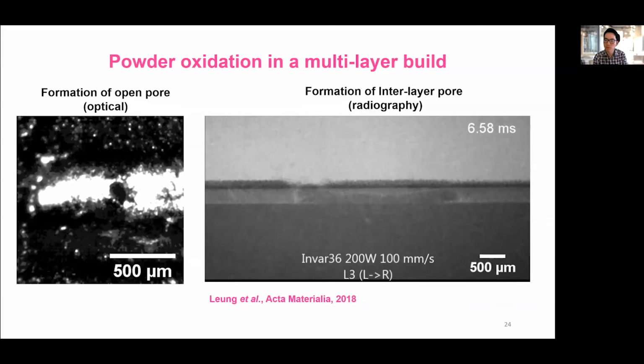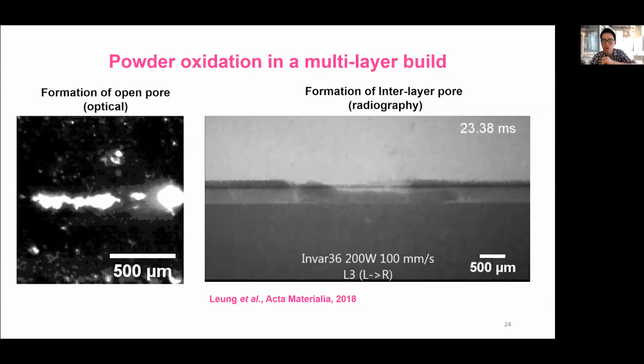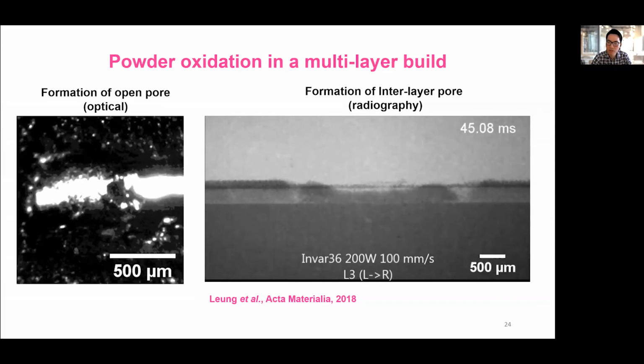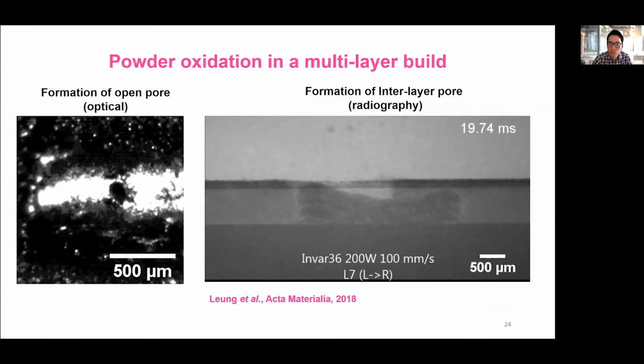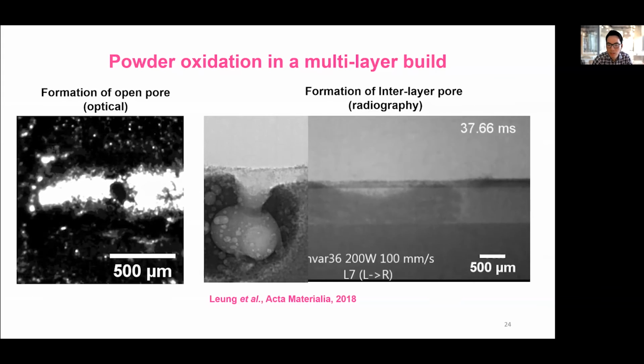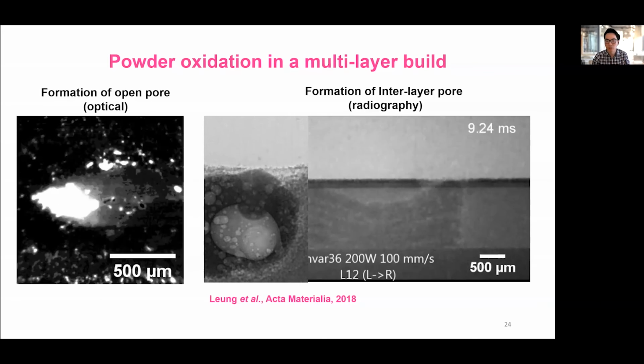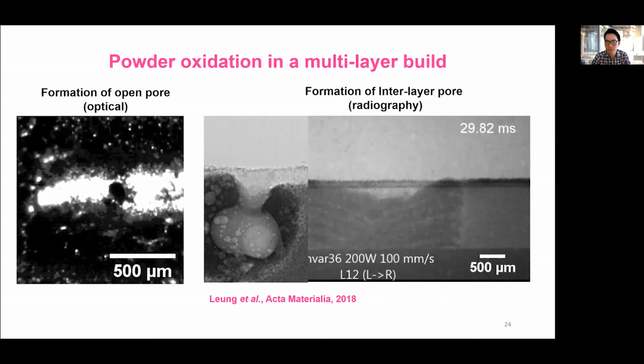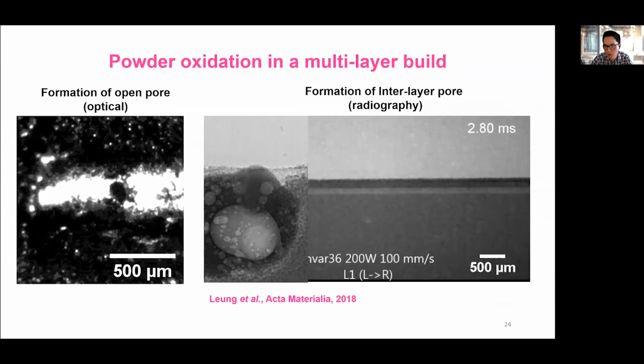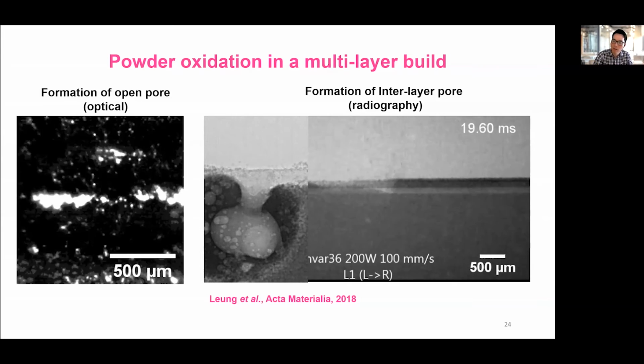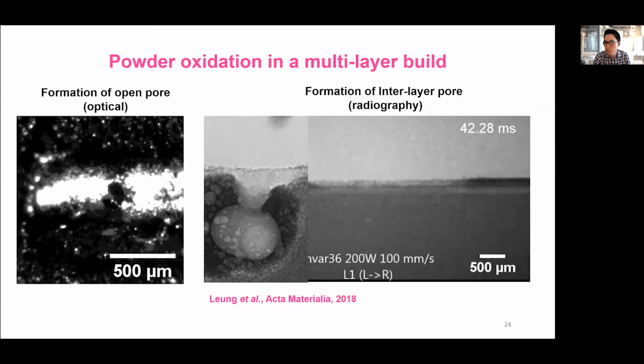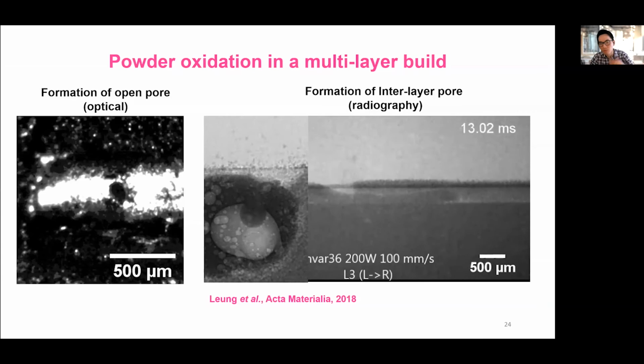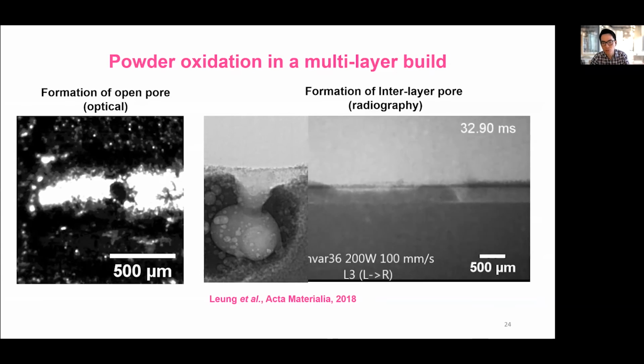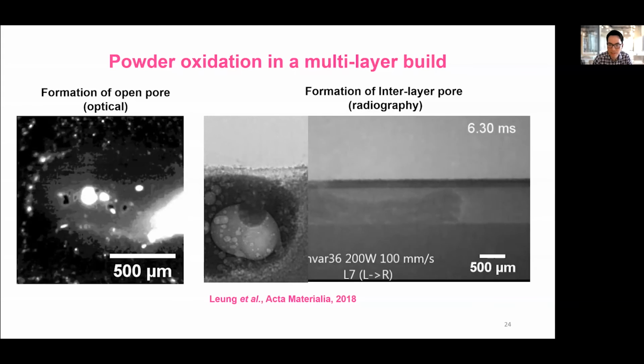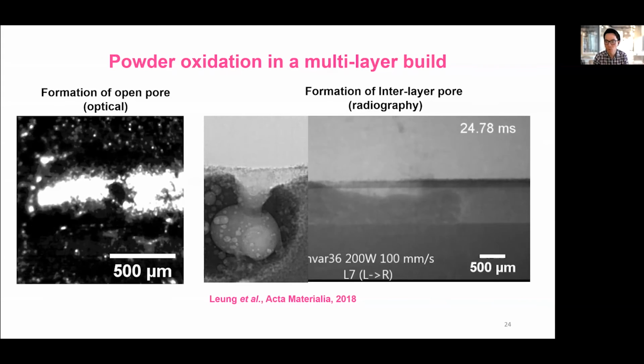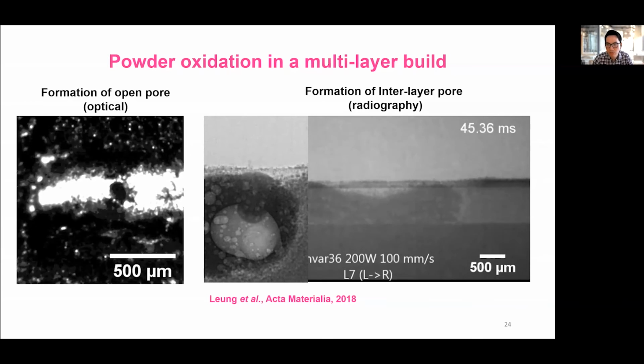What you can see is during this multi-layer build, sometimes you get this really black droplet just flying out in the middle of nowhere. And if we zoom in, what you can see is actually, if there is a pre-existing void and this void contains gas, when the laser is heating that gas up, it causes this ejection of liquid. And that explains why you get this droplet formation, or a possible mechanism. Whereas traditionally, if you only observe this melt surface, you won't be able to get this better understanding, which is why this technique our group has been championing and developing is really, really powerful.